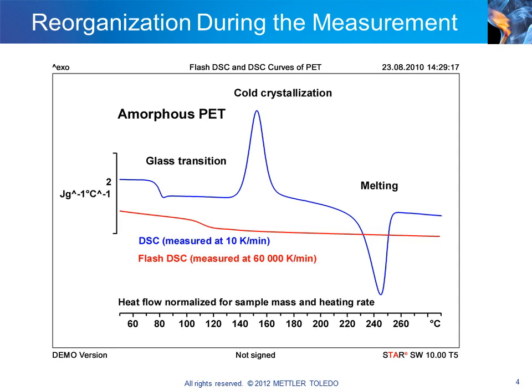Firstly, if you want to investigate the behavior of materials in technical processes, such as crystallization processes in injection molding, the heating rates used for the measurement must be comparable to those that occur in the actual process. Secondly, to perform such measurements, we need a DSC instrument that can measure at a very wide range of heating and cooling rates, in particular at high rates of about 100 to 1000 degrees per second. Here, conventional DSC instruments have a performance limitation because their maximum heating rates are only about several hundred degrees per minute. In other words, they are about 100 times too slow. They do, however, have the advantage that larger samples can be measured in crucibles.